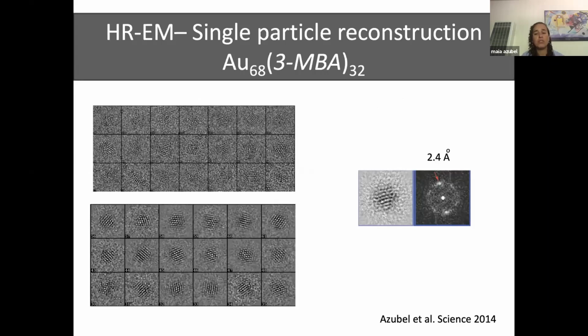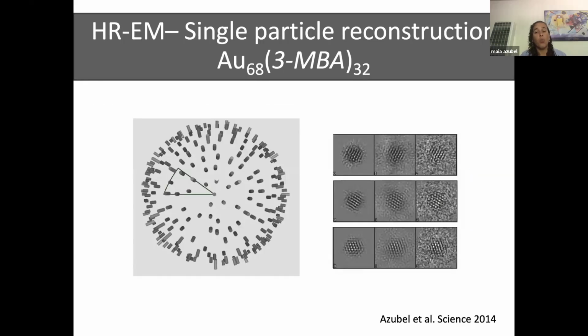When I took the 3D structure and I took a cross section and computed the Fourier transform, it was very nice to see that there were spots to 2.4 angstrom. So yes, this was the structure of a gold nanoparticle, so atomic resolution with an aberration corrected microscope. One thing that is very important is to see whether or not all the steps that you're taking make sense.